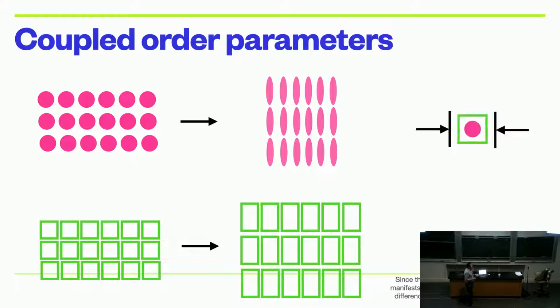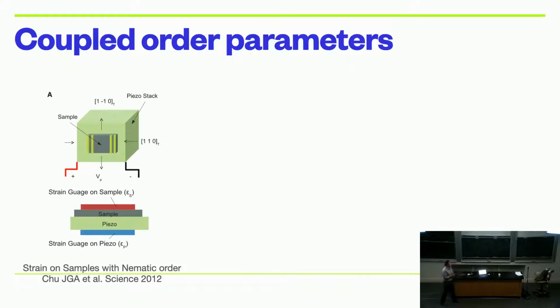Why is that important? Because you can imagine if I start with my square lattice with my electrons in the middle, and I squeeze it in one direction, then that's basically trying to turn the square into a rectangle, but it's going to have a response in the electrons themselves. And so as a result, by coupling to the lattice with some strain, I can actually couple to the nematicity of the electrons themselves. And that's a technique that we actually used while I was a postdoc at Stanford when we were studying some anisotropic superconductors known as the iron-based superconductors.